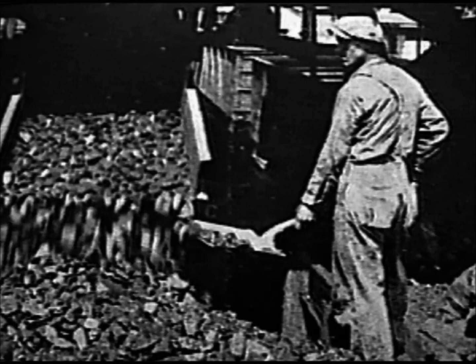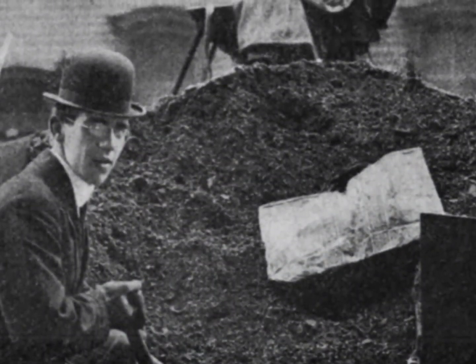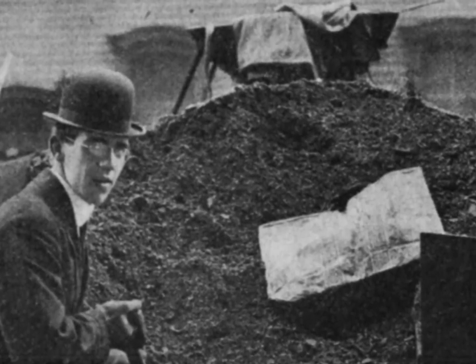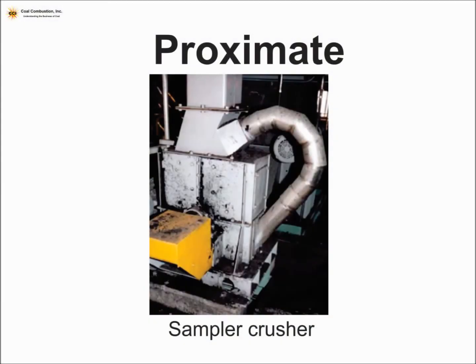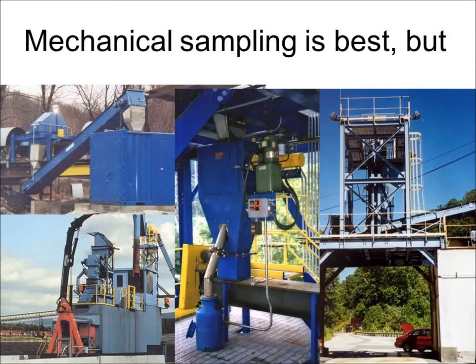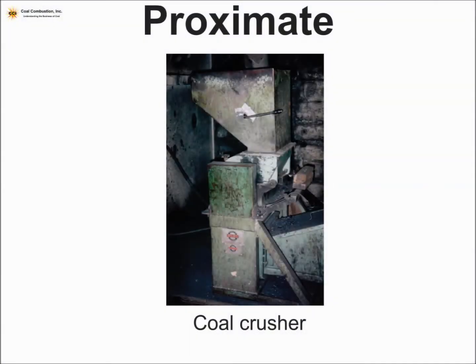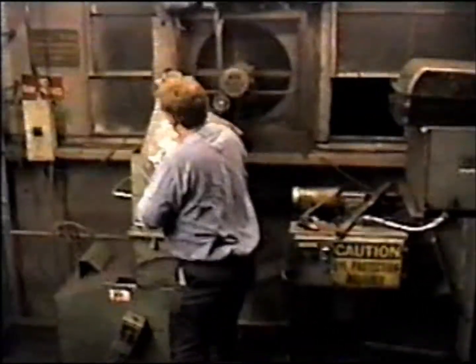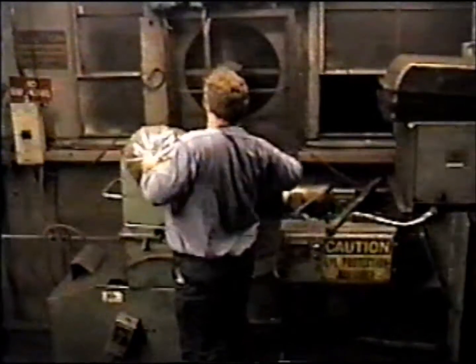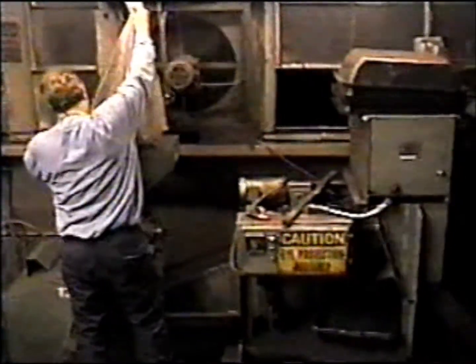We've got to go get a sample before it even gets to the lab. Going after the coal sample can be hard work, and you have to have integrity and trust in the people doing the sampling work. It's not usually hand sampled anymore — we usually take a mechanical sample. Keep in mind that all mechanical samplers generally have a crusher in them, and crushing dries out the sample. So coals that are suspect high moisture, wet, or low rank high moisture coals all suffer from this crushing and the potential of drying the sample, which gives a lower moisture and higher BTU value in the sample reported from the lab.